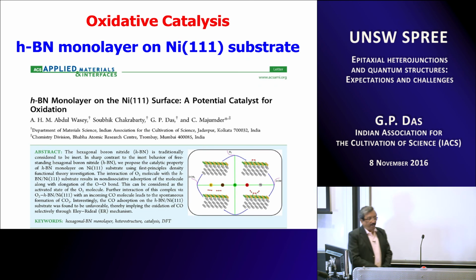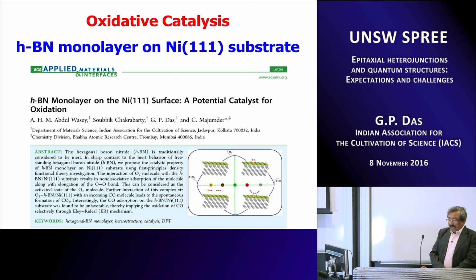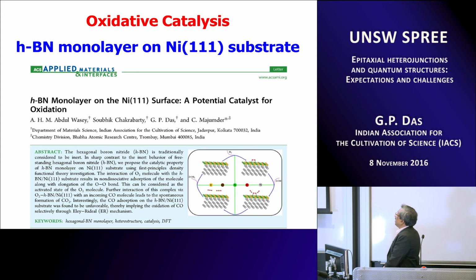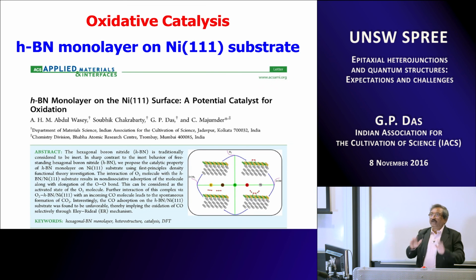So, okay. I would like to take this example of oxidative catalysis. This is something which is again a very interesting manifestation of interface induced phenomena. Hexagonal boron nitride is an inert material in the sense that if you try to bring oxygen onto a hexagonal boron nitride surface, it will not like to get adhered.